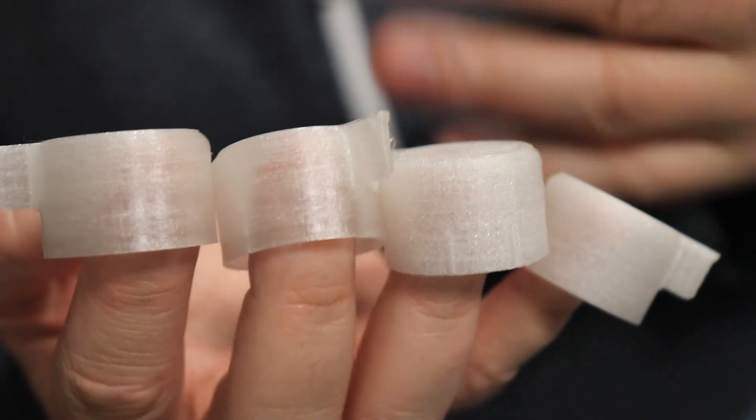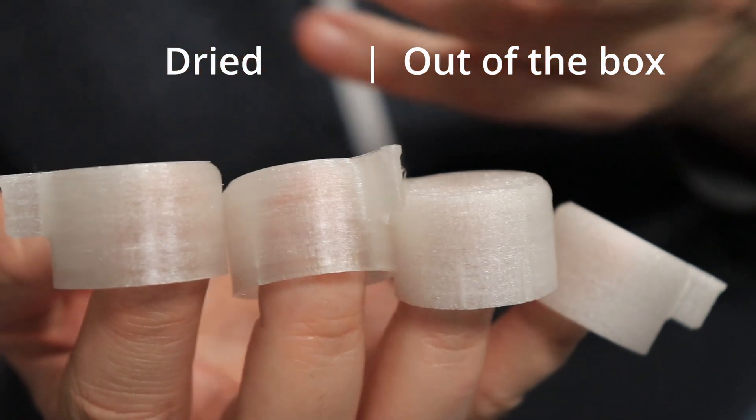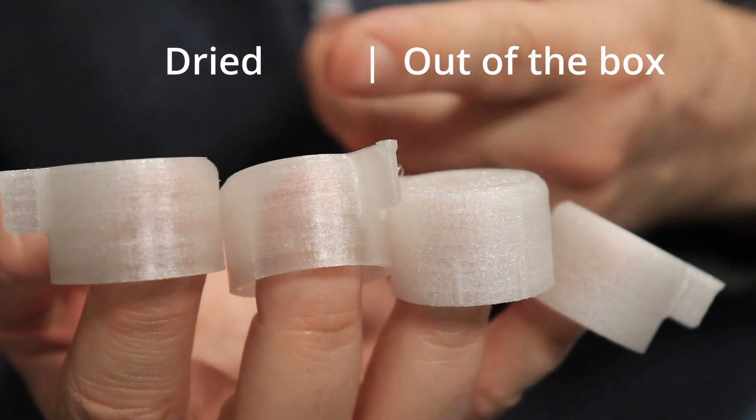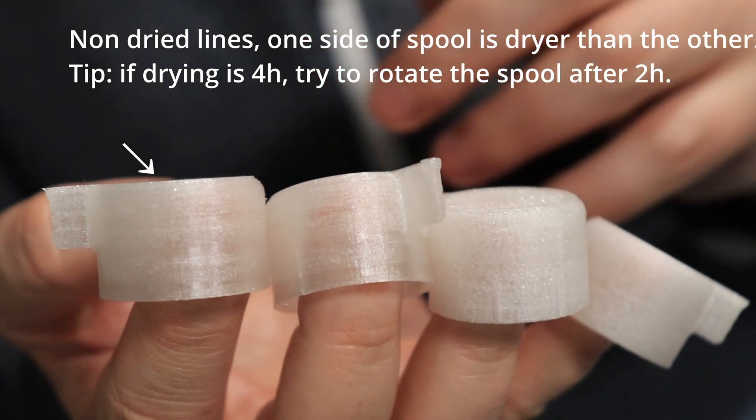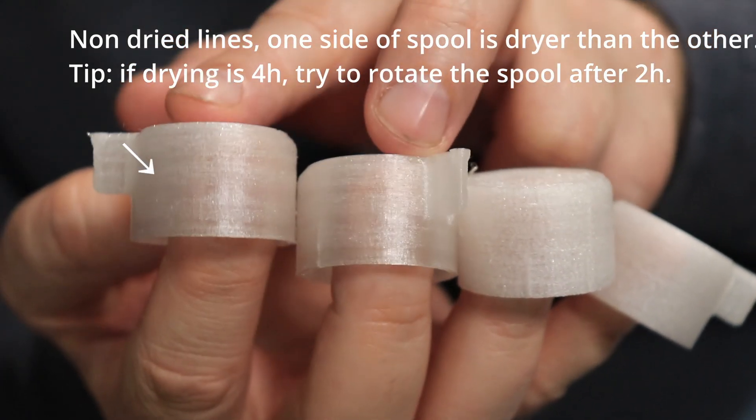Wow this is a great example of how important the filament dryer is. Unfortunately it looks like this filament is full of moisture out of the box, but good news is that even the cheapest filament dryer can dry it and you will get much nicer printing.